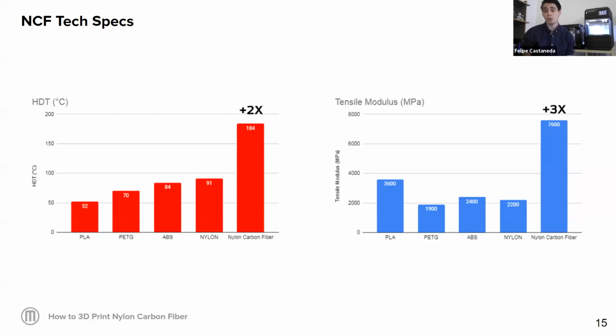And then when talking about the tensile modulus, you're also getting an impressive increase in performance, right? Almost 3 times. You see PLA, these are all megapascals. So PLA, PETG, ABS, nylon. Now, one of the interesting things here to know is that you would probably, at a glance, assume that if just comparing the most standard polymers here, PLA and ABS, PLA might be a little bit less strong than ABS. However, at least in my experience, and this is one thing that I was wondering when I first saw these numbers, what happens with PLA is that it's a much stiffer material for some reason when it comes out of the printer, right? And I know that we've all stomped on a Lego brick, and we know how strong ABS can be because of that. But PLA is definitely an interesting material that sometimes gets underappreciated. But it all depends on the application, right?